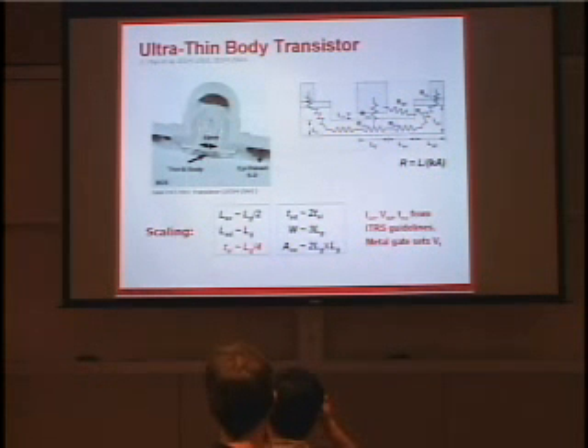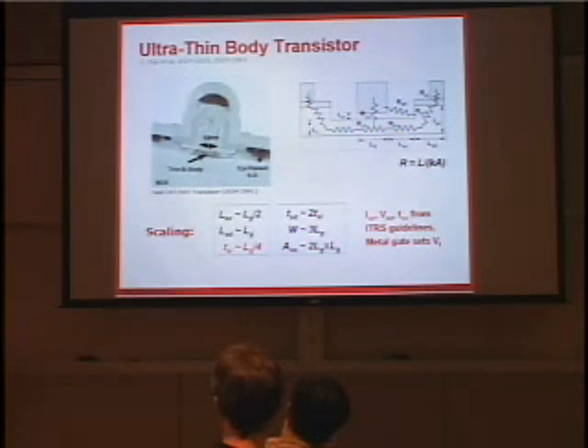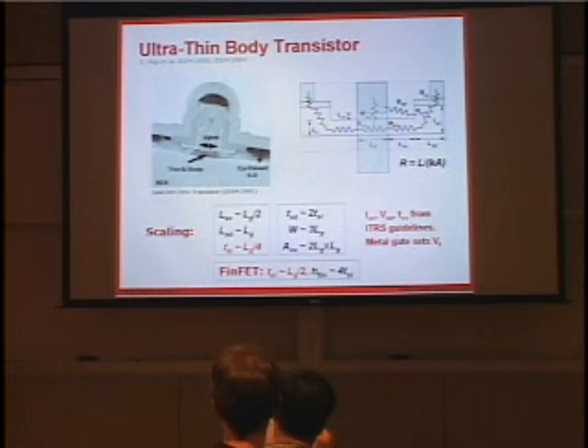And on the right is essentially a thermal circuit model representation of this transistor, of how the heat might flow around it, now that we know that heat is generated. And the resistances can be computed fairly simply using a lumped resistance model. One of the important things to realize here for the scaling study is that the thickness of the silicon layer, which I've highlighted in red, is generally assumed to scale as the gate length divided by 4. This is for purely electrostatic reasons. This is how you get a fully depleted substrate, and this is how you get good short channel characteristics.